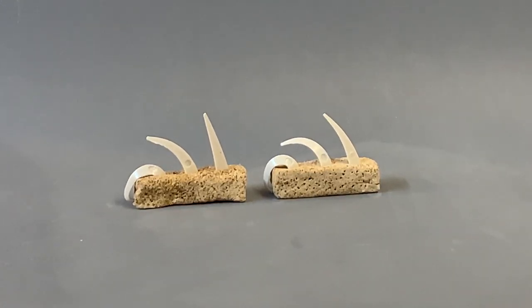It was a very successful firing getting to the right temp. Just for fun, I put two pyrometers at the bottom of the kiln to see what would happen, and I followed them all the way up — they got to 2200 degrees and quit getting any hotter, but I know the kiln got hotter because the cones show me that it did. Also, all the way up, one pyrometer read 70 degrees hotter than the other. The moral of this story is that I don't really trust pyrometers — I trust cones a lot more. They're much more accurate, and you can put them all over the kiln to learn exactly where the hot spots and cool spots are.